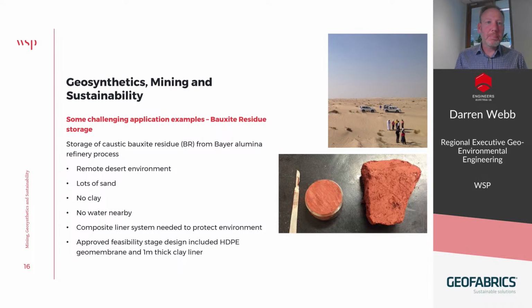Another example. So this is for bauxite residue storage. Bauxite residue, most of the time, is a result of the Bayer alumina refinery process. So it results in a very caustic or high pH residue, which is the bauxite residue, which requires storing. And so this facility was in a remote desert environment with lots of sand, no clay, which is what you might expect in that environment, and no nearby water source.